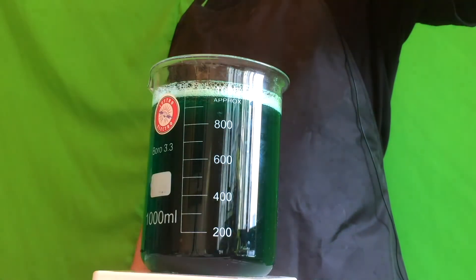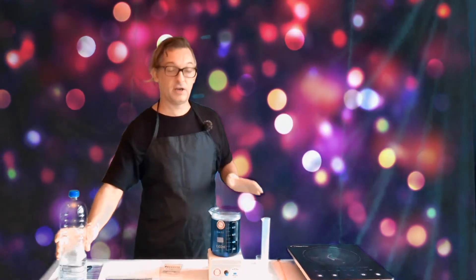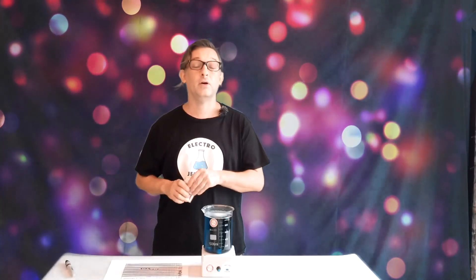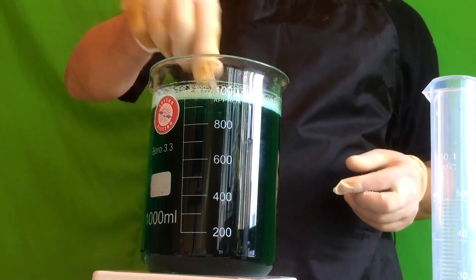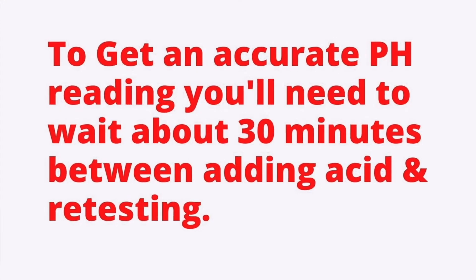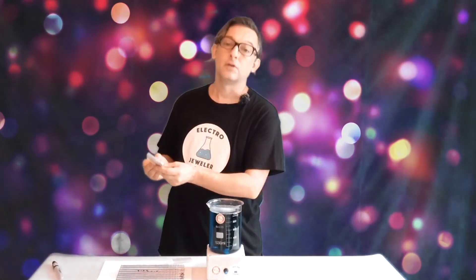Run that with the magnetic stirrer for about 10 to 15 minutes, then check the pH again to see if you're spot on or need to add a little more sulfuric acid. Testing the pH again — it's spot on at 3.5. If you don't get the pH right the first time, just follow the chart and repeat the steps until you have it right. It's necessary to wait about 20 to 30 minutes between each pH adjustment to get an accurate reading and allow the acid to fully integrate into the nickel electroplating solution.